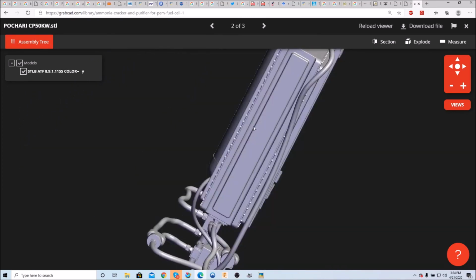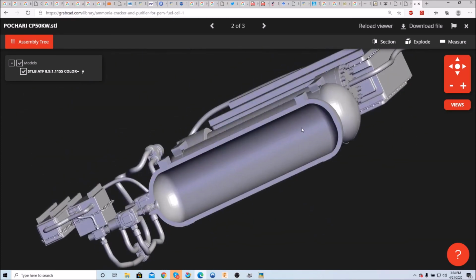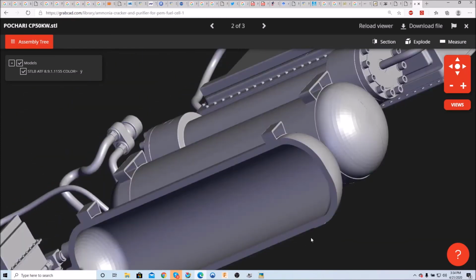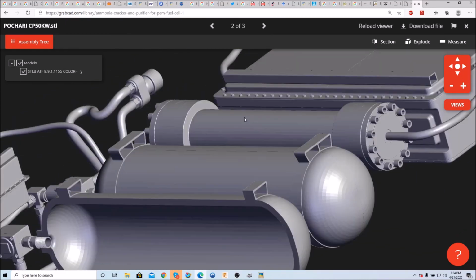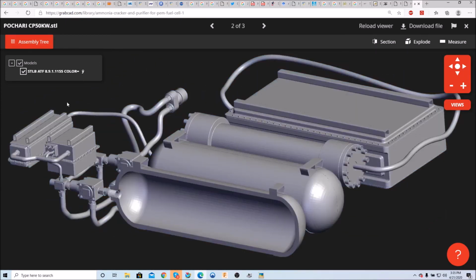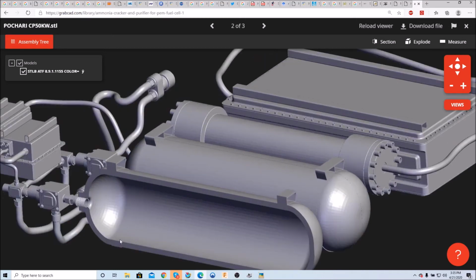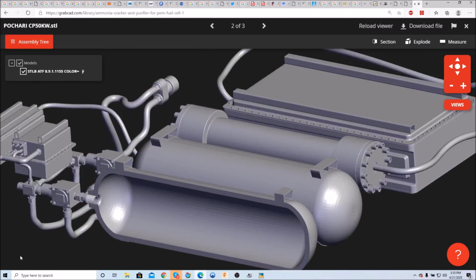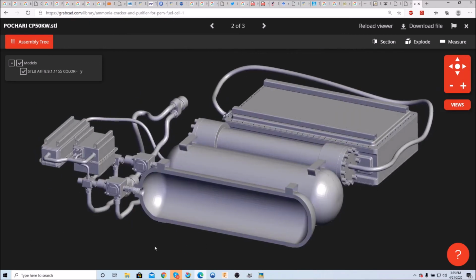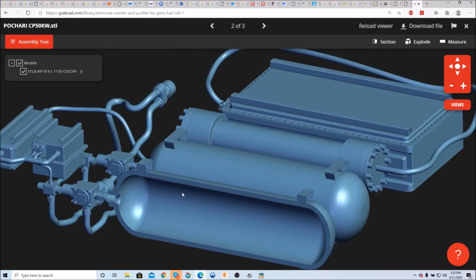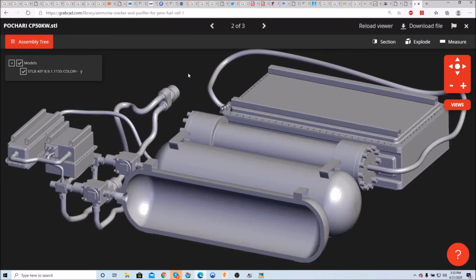And our tanks, we went with, I think, 3/4 of an inch of ultra-high molecular weight polyethylene. And again, the rationale behind that is that it was involved in a collision. A piece of metal being hurled at a high velocity would potentially puncture through the thin-walled aluminum tank. With the ultra-high molecular weight polyethylene, it would absorb that energy. It would probably permanently deform the tank, the aluminum substructure of the tank, but the polyethylene would prevent it from fracturing and reduce the risk of releasing ammonia.